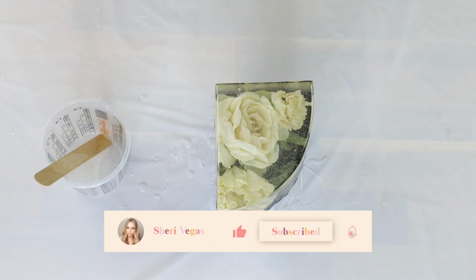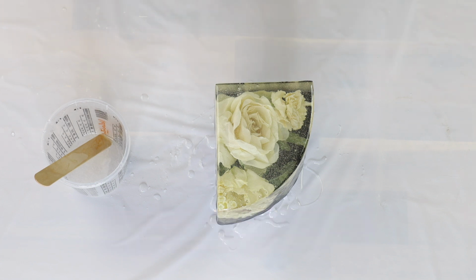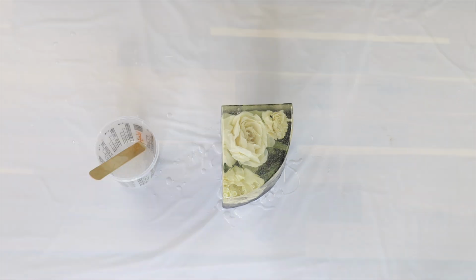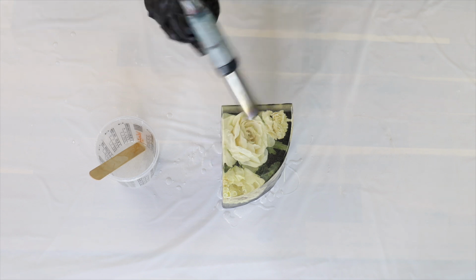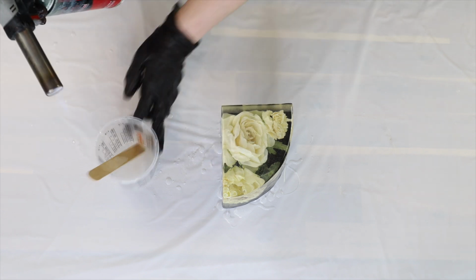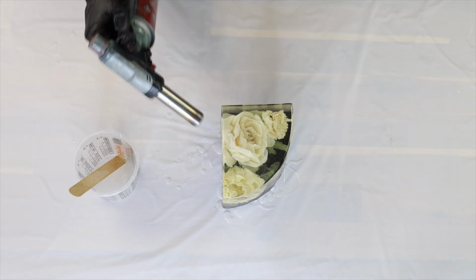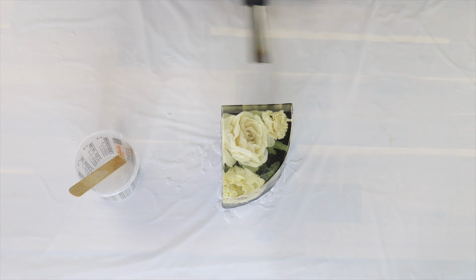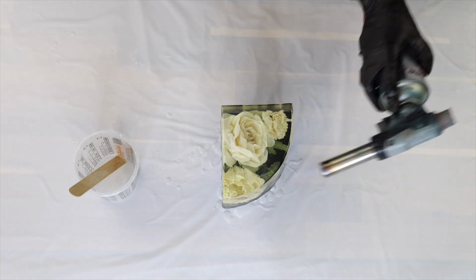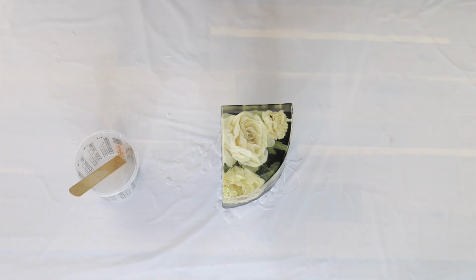Now with this, I always use a blowtorch to pop any of my bubbles over a heat gun, because a blowtorch is a lot hotter, it's more effective at popping the bubbles, and it's also not going to blow the resin off my piece. I will always torch my piece multiple times throughout this top coating process, so I like to do it within the first 5 minutes of applying my top coat to just pop those initial bubbles. I then wait another 10 minutes to go back in and repeat.